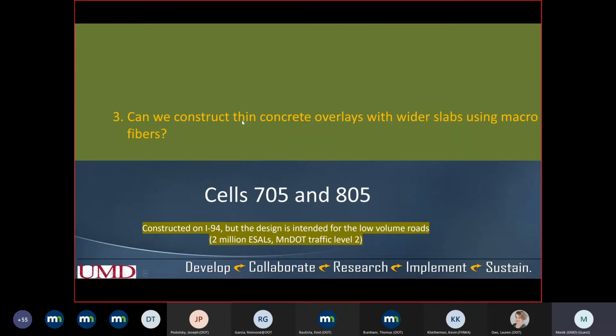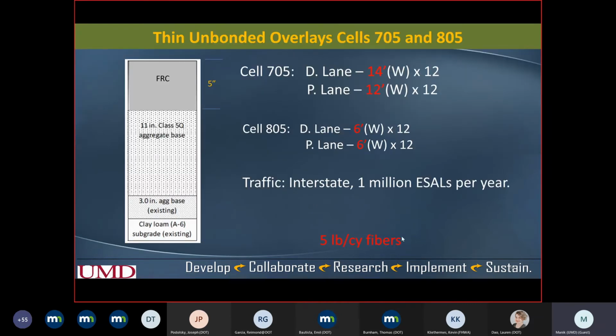Okay, question number 3. Can we construct thin concrete overlays with wider slabs using macro fibers? For that, the data of cells 705 and 805 were used. Again, those cells were constructed on interstate traffic, I-94. Now 705 had larger slabs, 14 feet by 12 feet, and the passing lane was the slab size. The width of the slab was 6 feet, or half of the other cell, 705. Again, interstate traffic, 1 million ESALs per year, and the fiber used here was 5 pounds.